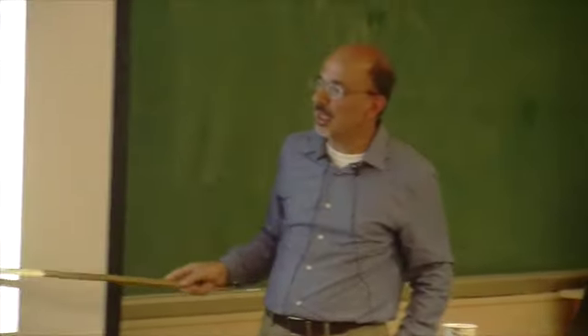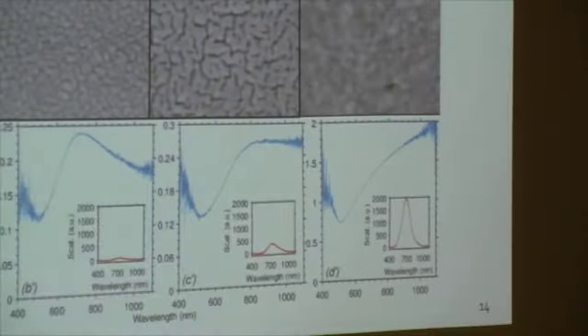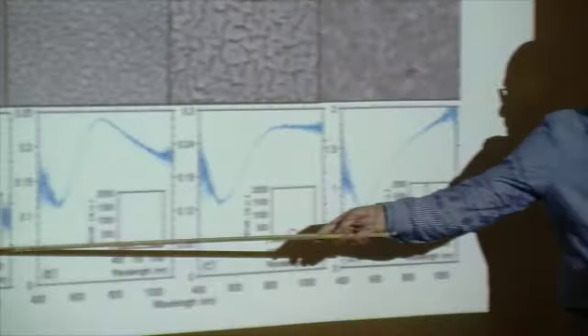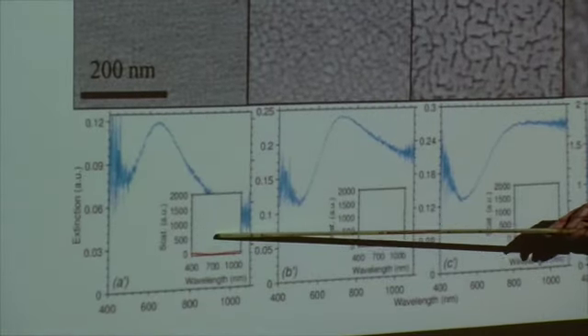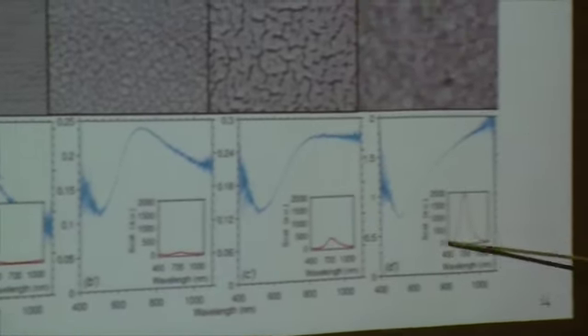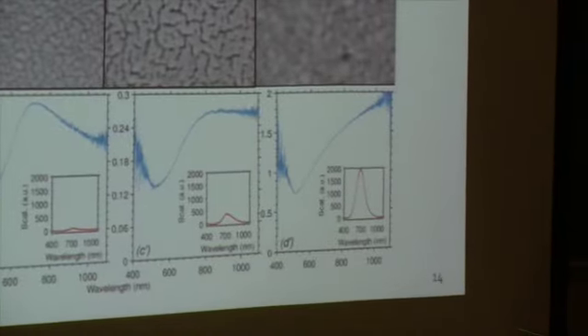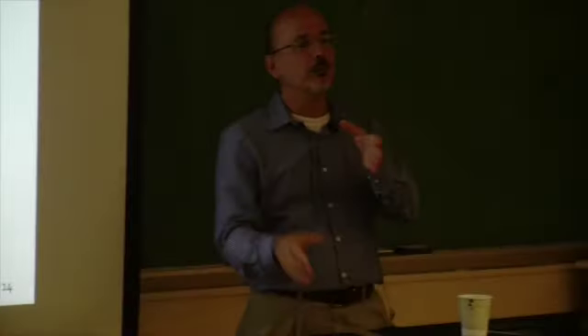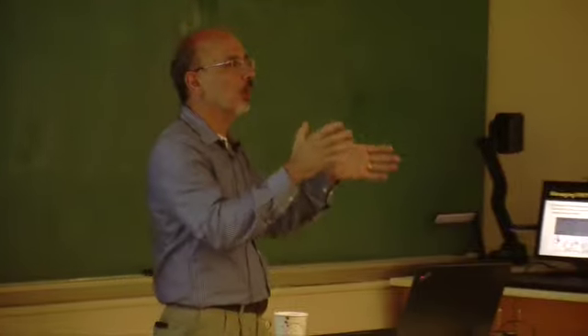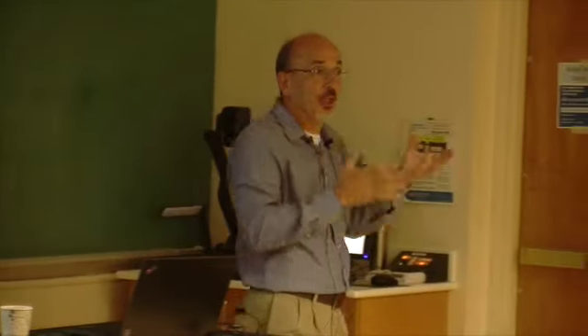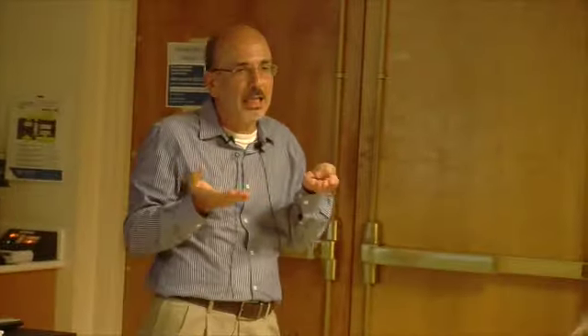But if you look at the dark field of the light coming from the top, you see that there is nothing here. So there is no field enhancement. But here you can see a very strong peak, and it suggests that 40 nanometers of gold provides a good amount of field enhancement. So what we did is play around with the balance between FRET and field enhancement to our advantage.